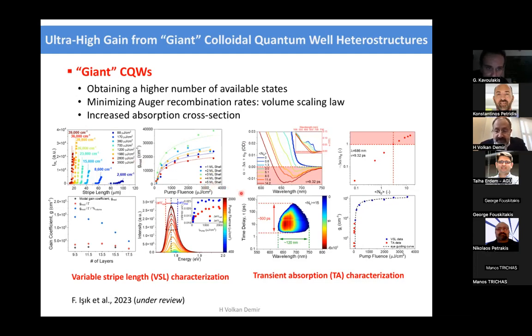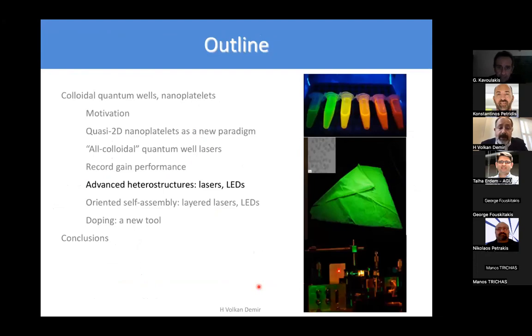And what we observed is there's a sweet spot where we can achieve the highest. And we were able to confirm this using variable stripe length characterization and transient absorption characterization. And we would like to push this further and use this very promising material system again for gain purposes.